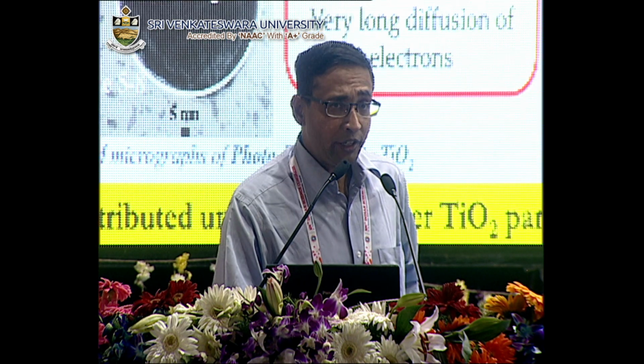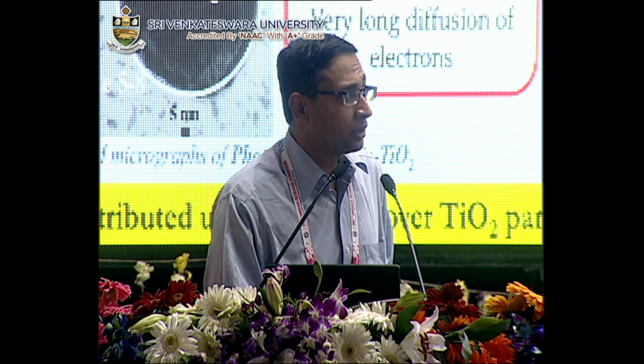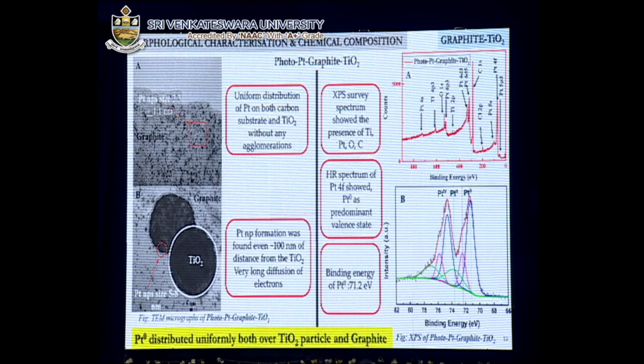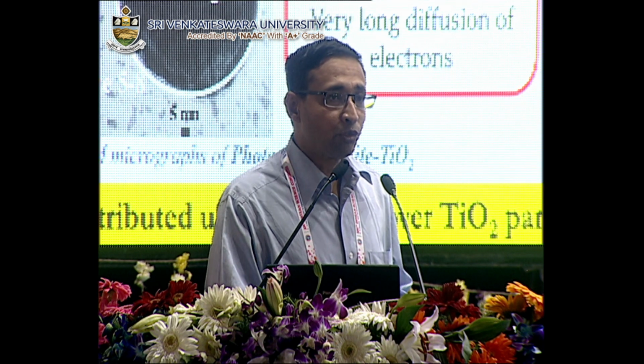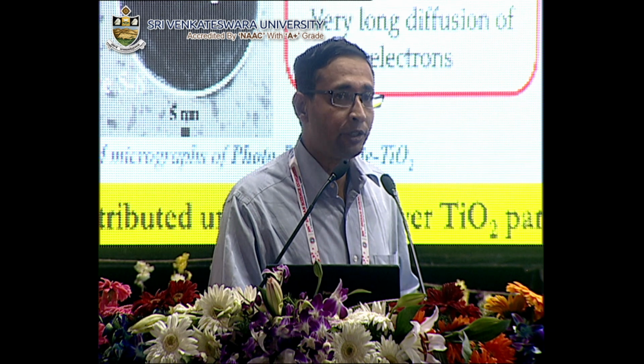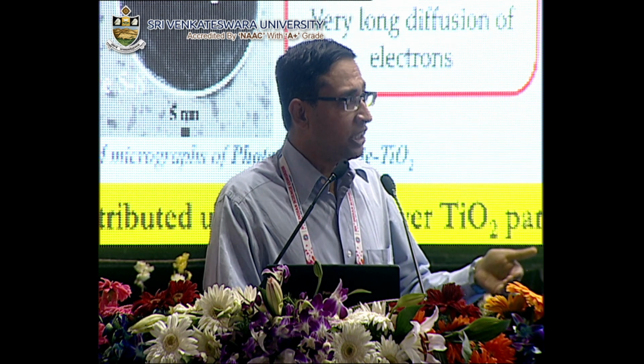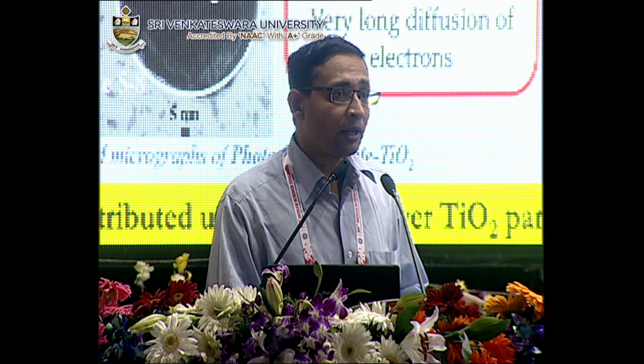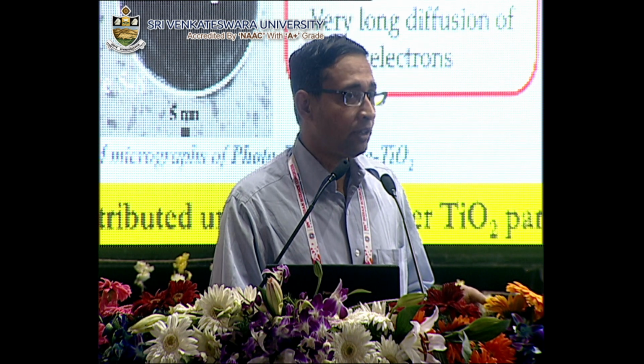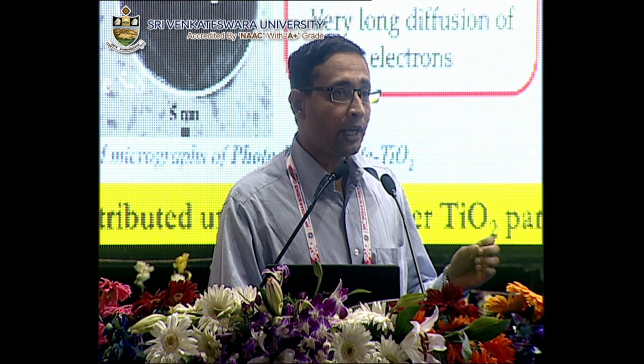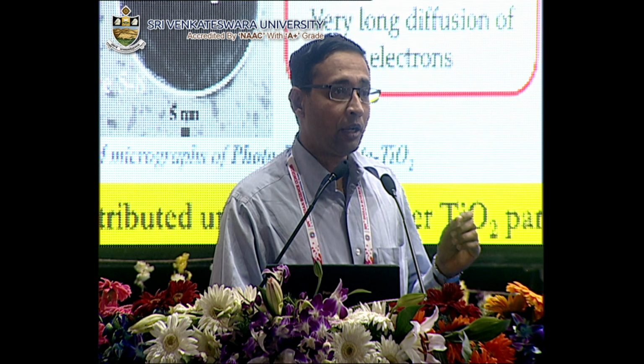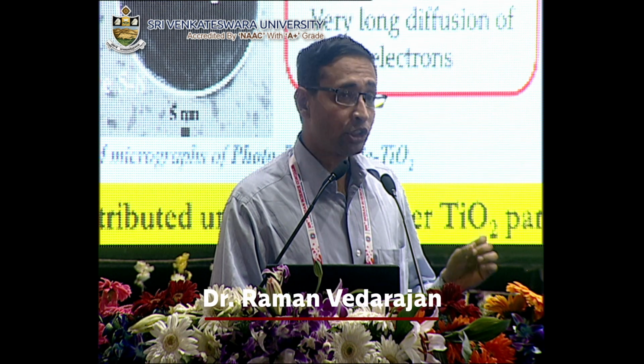Whereas when we finish the experiment and do the characterization, we see that the TiO2 and the graphite are studded with a lot of black particles. These black particles are called photodeposits because we don't know whether the platinum is completely converted or not. So these photodeposits were analyzed by a method called XPS, X-ray photoelectron spectroscopy, and we found that these particles in fact showed the presence of platinum.